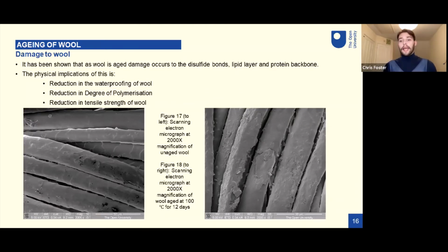Now, the physical implications of this can be, one, a reduction in the waterproofing of the fibre. I've seen this in my own work. I can do some contact angle measurements. So you put the textile with a drop of water and you use a high-speed camera to measure how that water interacts. And you see that with the aged samples, the water is absorbed very quickly, whereas with the unaged, it kind of stays more on the surface. And this is indicative that the wool is becoming more hydrophilic, and therefore that protective layer is being damaged.